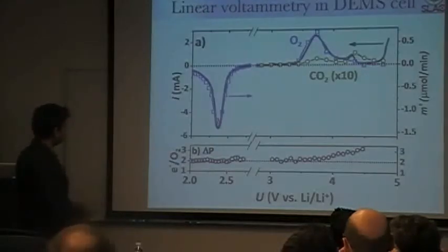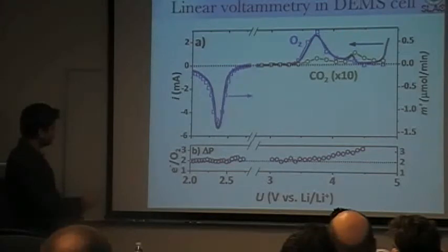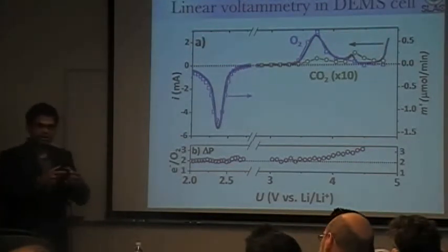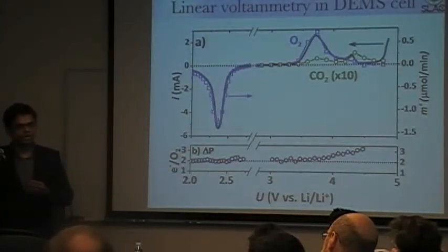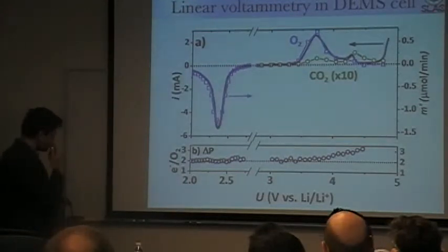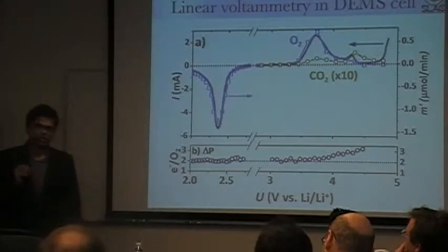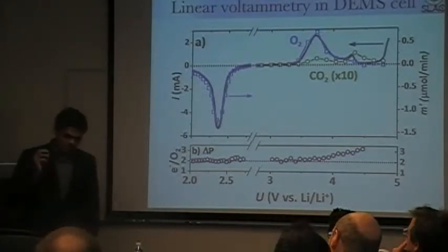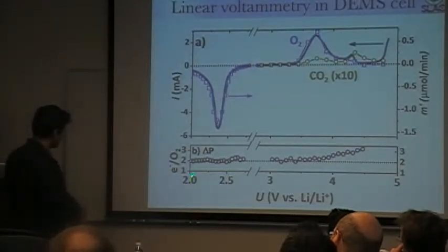This experiment is done in a DEMS cell — done by our collaborators at IBM — where they design a battery and hook it up to a mass spectrometer, then calibrate what gas products are consumed and what are evolved. From this you can extract a very important parameter: electrons per oxygen. This is really what you want to know — how many electrons are going towards the desired reaction — because we want to minimize parasitic reactions as much as possible.